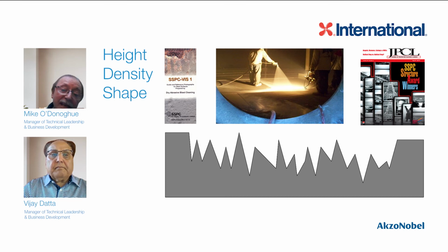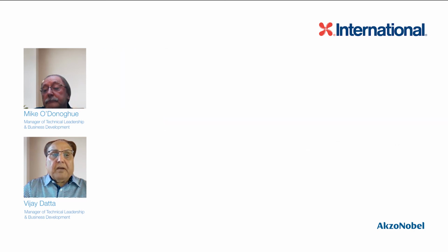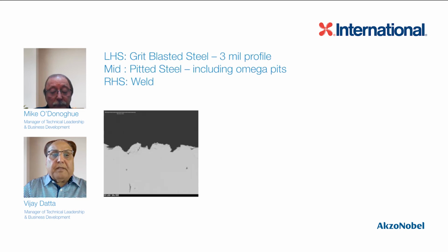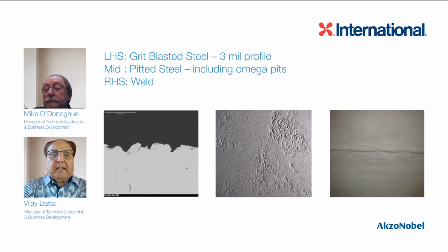And we've written papers about this, actually, in the old days. It was called Angels and Demons, and we talk about the impact of the actual profile on the coating performance. Now, here are steel profiles. The left-hand side is a grit blasted steel with a 3 mil profile. As you can see, it gives us a very jagged profile, Mike, which you mentioned, and it's really required for the solvent-free epoxy coating.